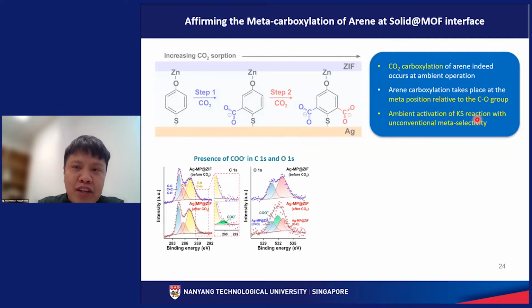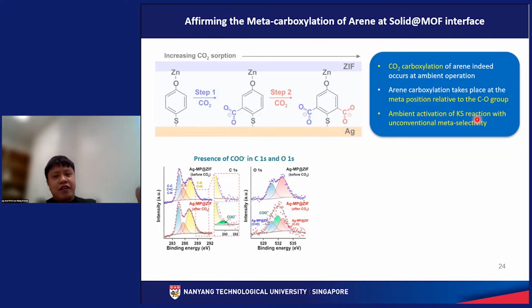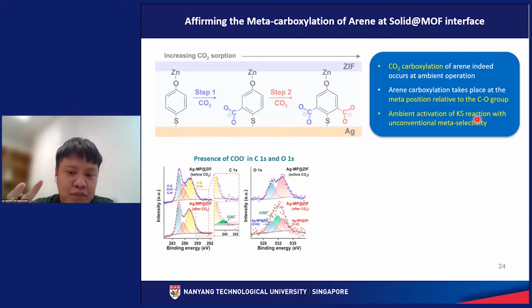So using SERS and DFT alone is simply not enough, because that's what the reviewer will always ask. So that is why we try to further characterize our system using XPS before and after CO2 flow. So for this case, we use C1s and O1s characterization. So in the case of C1s, before CO2 flow, we do not see any carboxylate environment over here. So only after CO2 flow for 105 minutes, we are able to see the carboxylate environment in our C1s feature.